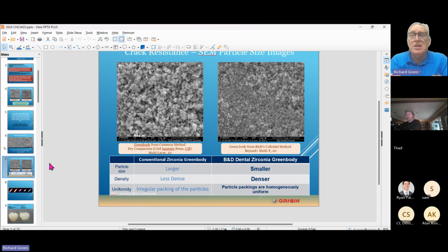We've done of all on fours with our fast cycle, which is about 3.5 hours. They've been strong enough and translucent. They're in people's mouths now. So by using the 1 hour firing cycle, you can create greater value for your laboratory to your doctors by being able to get crowns out quicker. You can still charge them extra for the quick crowns, but at least you have the opportunity to do this much more easily.